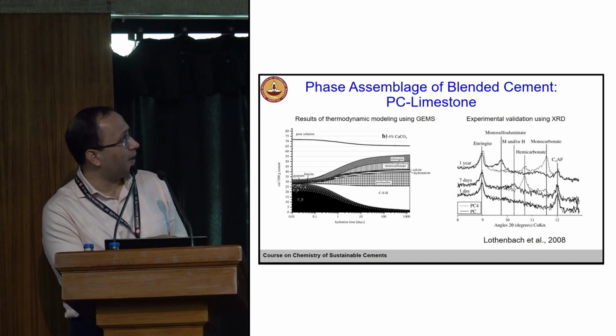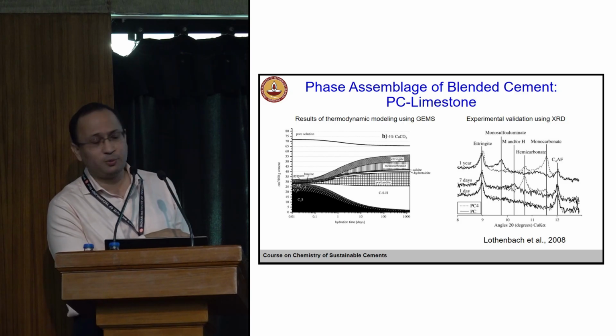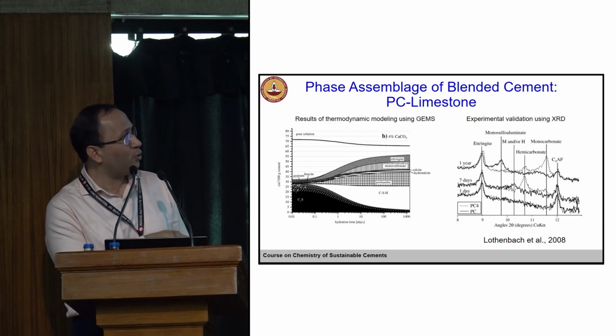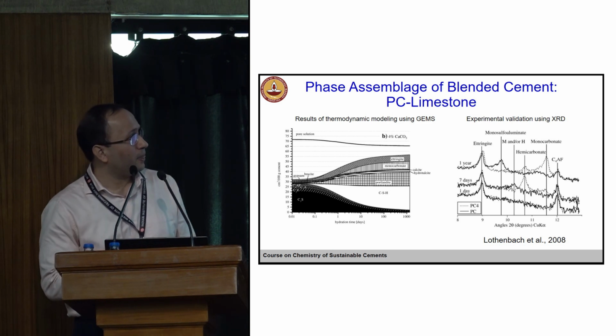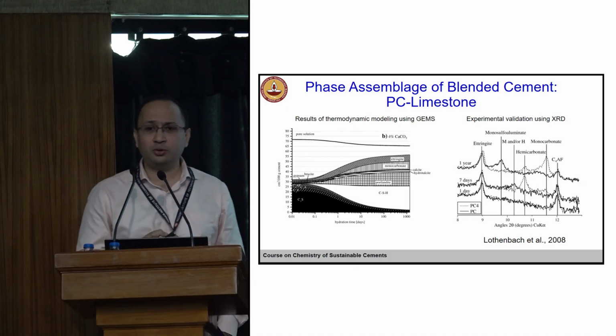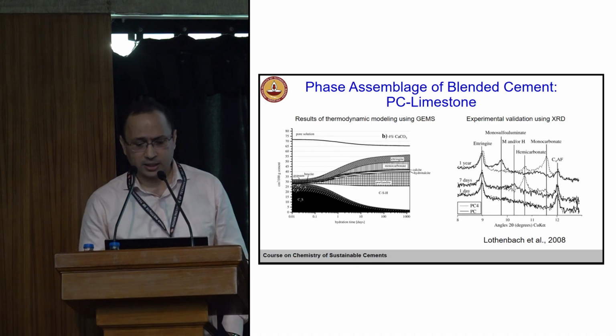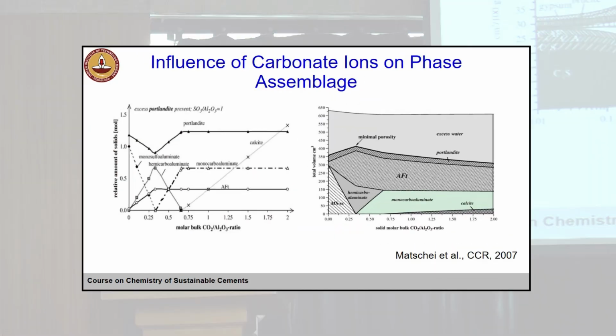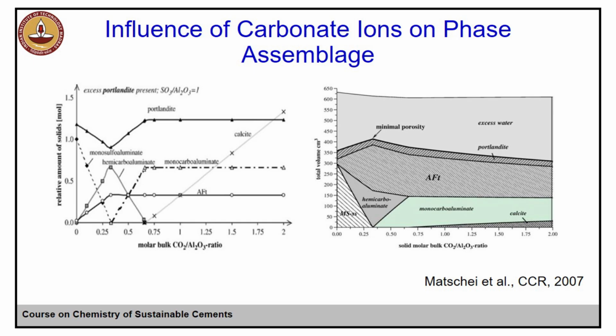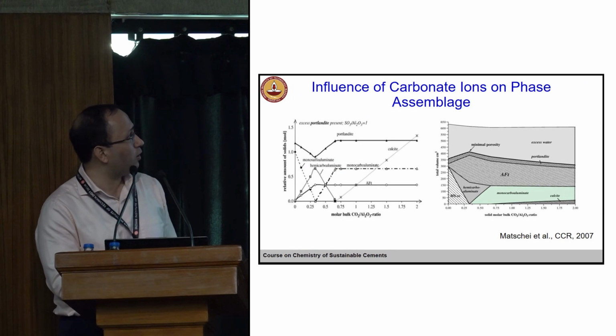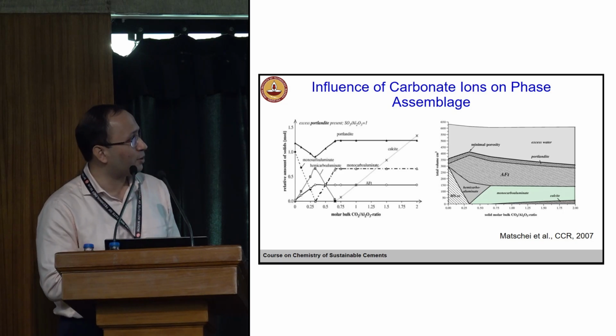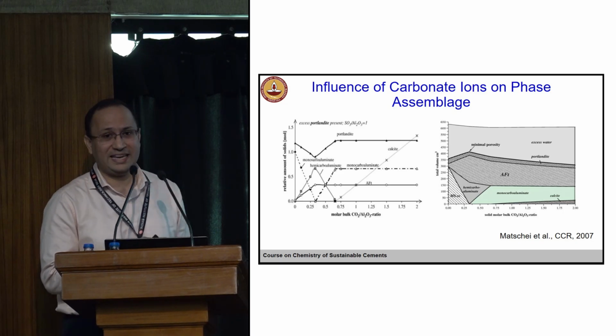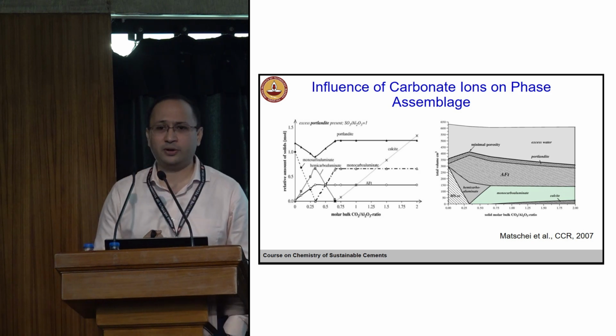So you see here, with the addition of 4% calcium carbonate, how the phase assemblage changes. So you have formation of monocarbonate in this case, in addition to ettringite. So this is what happens, and we can also experimentally verify what kind of changes are brought in with the addition of limestone. But one interesting aspect, which again has implications on the system when you have calcined clay, for example, is the role of carbonate ions. It stabilizes AFt. So what happens in a conventional Portland cement system?